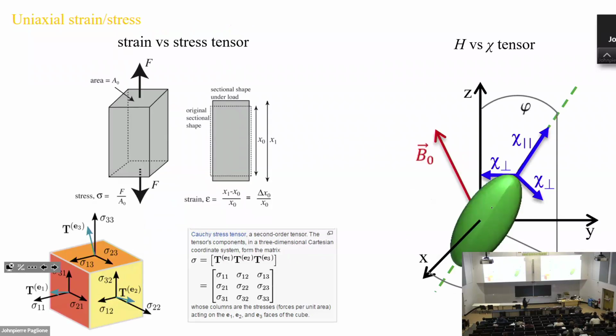With uniaxial strain, when you apply a strain to the sample, it will respond not only in that direction, but also in the other directions. So the stress is actually a tensor. In some sense, this is like a magnetic field versus magnetic susceptibility. So you can get more information out of this type of experiment.